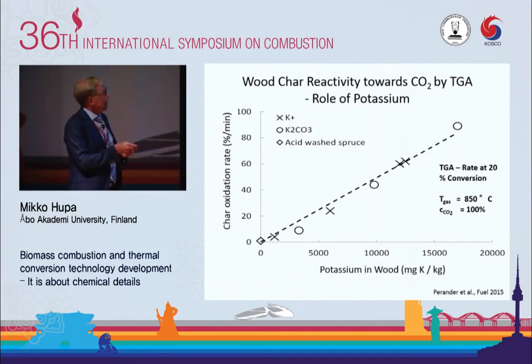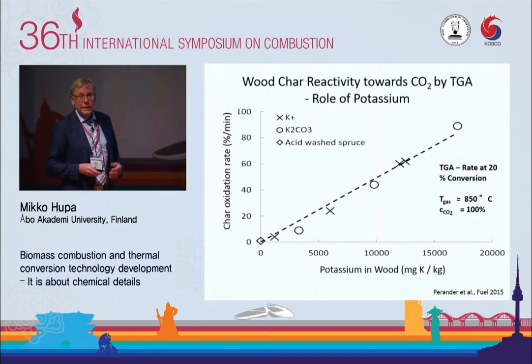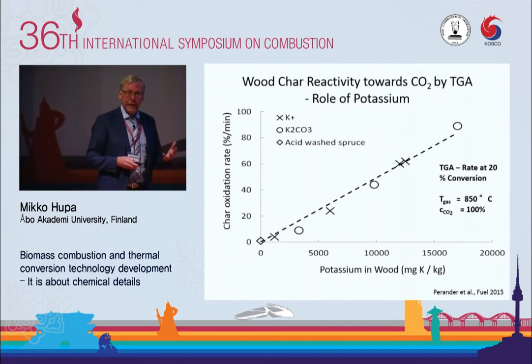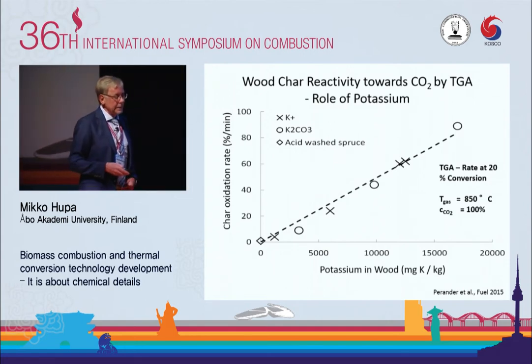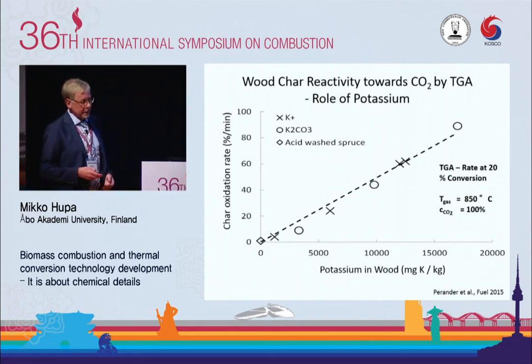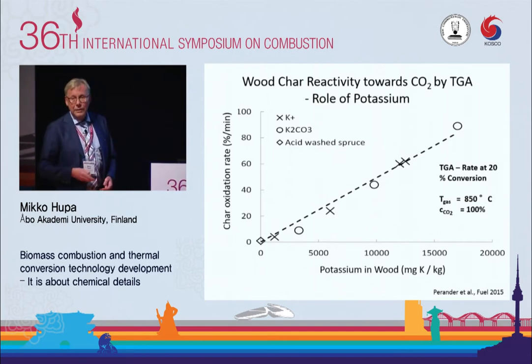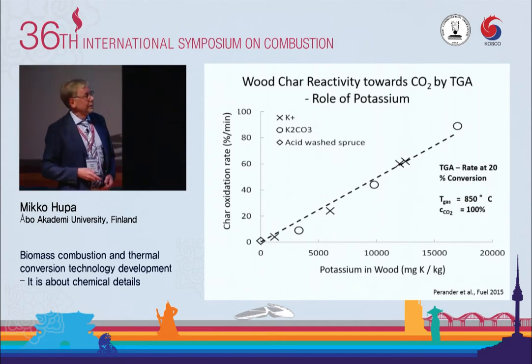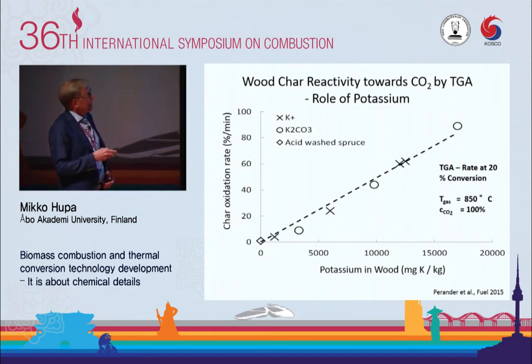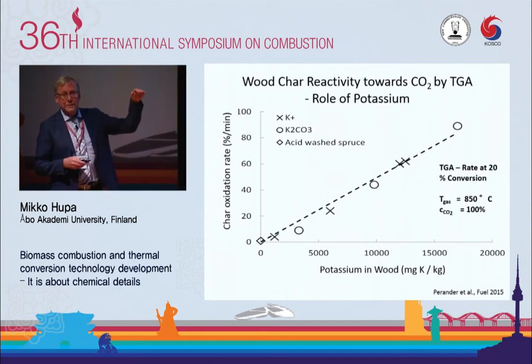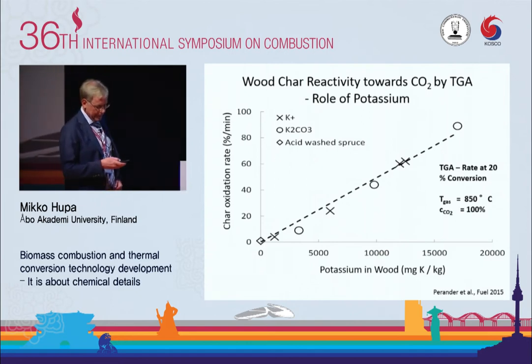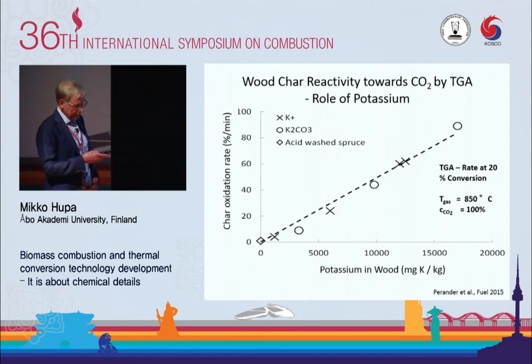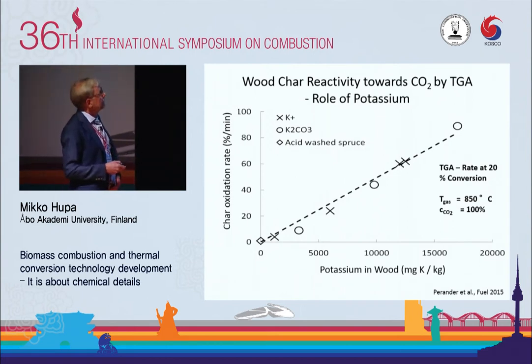And then we added potassium, even in different forms, to the fuel, produced the char, and measured the char reactivity by TGA. And here you see the char oxidation rate, percent per minute. Now, this is not in air, this is in carbon dioxide, where the same reactivity is also easy to detect. And you see, in a funny way, almost linear correlation. We didn't add enough potassium to see it leveling out later. Definitely it will do that. This is just an interesting thing to learn, that it's so sensitive to the potassium content.